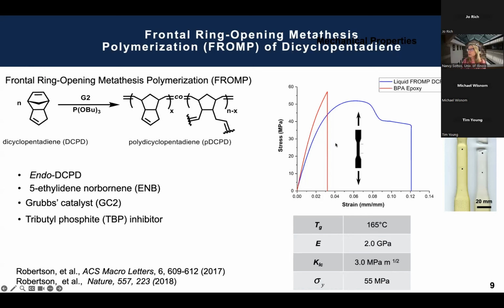What's nice about using a poly-DCPD is that once you cure it up, it's got really nice properties comparable to an aerospace grade epoxy, except that it is actually quite a bit tougher. It has a much higher fracture toughness. Modulus is a tiny bit lower than most epoxies, and significantly higher fracture toughness. And it's got actually a well-defined yield, which is also interesting in a cross-link system.